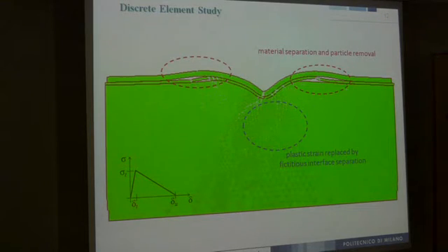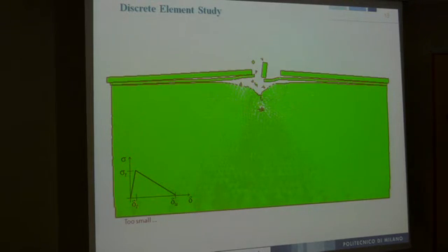The problem, as I was saying, is quite sensitive to parameters, and we just show you how the results change if we assume that this initial hardening phase of the interface is very small, consistent with typical brittle fracture phenomena. Then, as you can see, the results are quite different from the experiment. There is still clearly sliding across this interface, but the failure mode of this system, as you can realize from this picture, is much more brittle than it is in practice.